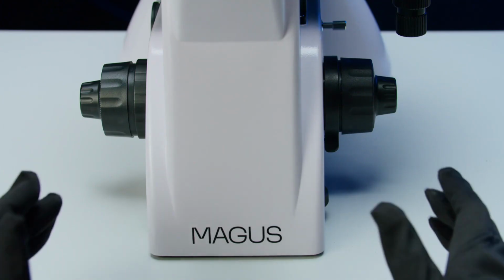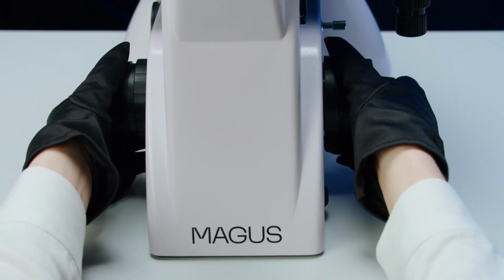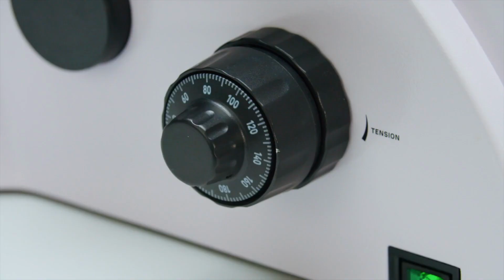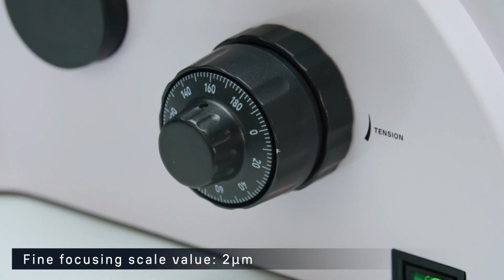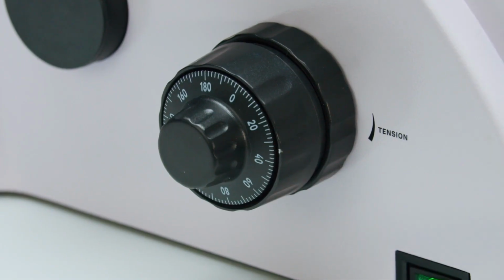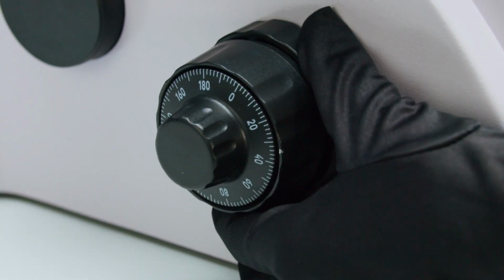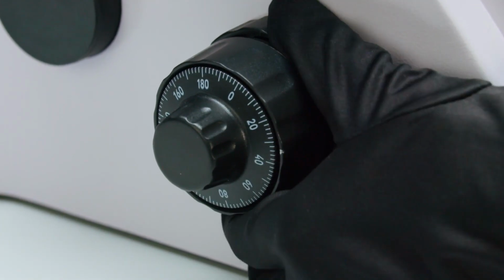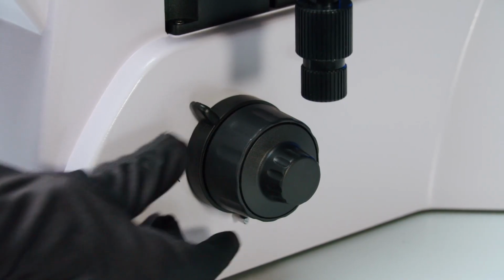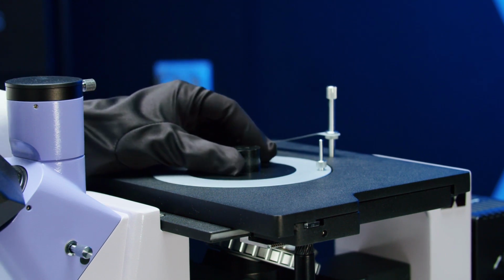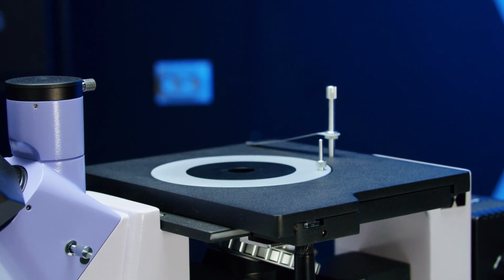The coaxial focusing mechanism combines coarse and fine adjustment, tension adjustment, travel adjustment, and coarse focus lock. The fine focus division value is 2 microns. With the ring on the left side, the user adjusts the coarse focus tension to a comfortable level for operation. The ring on the right side locks the coarse focus. This simplifies readjusting the microscope when changing the specimen.